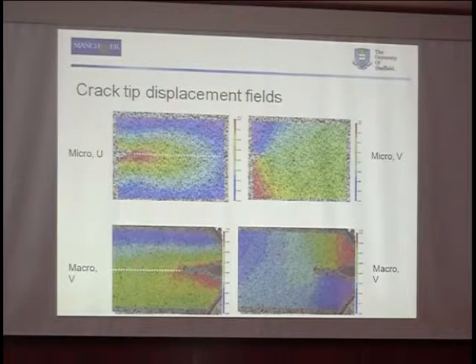And you probably can't see that well here, but if you look at the scaling there, the difference from that to that is only about 4 microns. So we get very detailed measurements of this field very close to the crack tip. Whereas from here, I think that's about 20 microns. But what I would say is, due to the optics and the distance of the camera and the field of view, for the fatigue crack loads, the displacements were near the limit of the DIC system for the 2D.